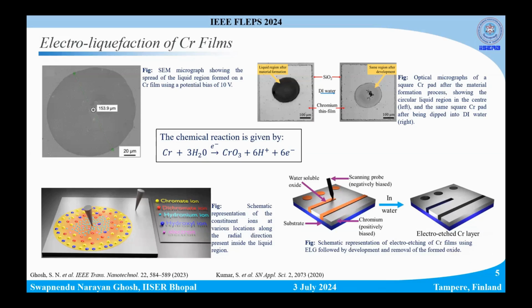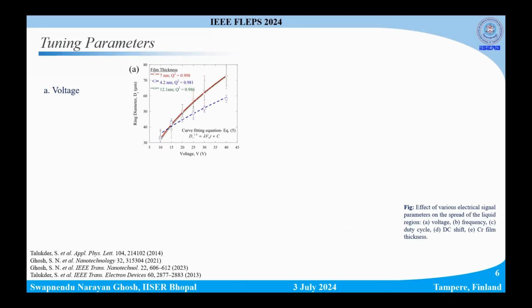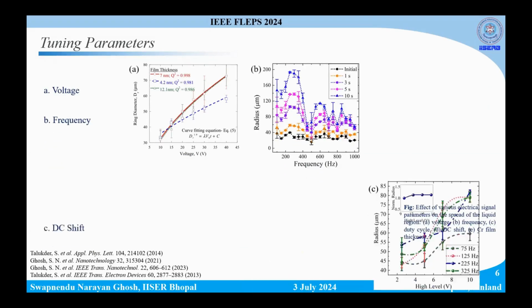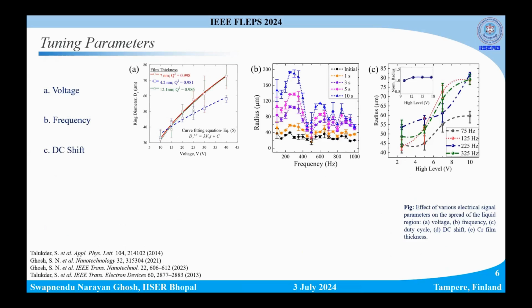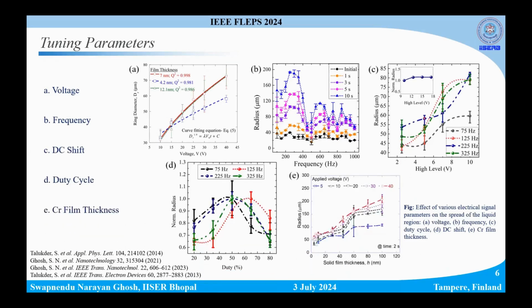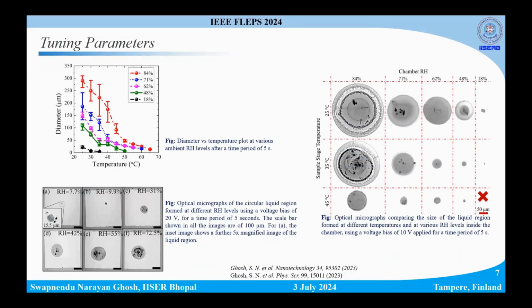I'll come back more to it, but first, let's look into the factors that can help tune the rate of oxidation or the spread of this oxide region. Some of the tuning parameters are, first, the strength of the electric field or voltage, the frequency if you are applying an AC signal, then the DC offset, the duty cycle, as well as the thickness of the chrome film. All of these are mostly electrical parameters. There is also the effect of relative humidity and the experimental temperature, and you can see how significantly both RH and temperature affect this oxidation process.